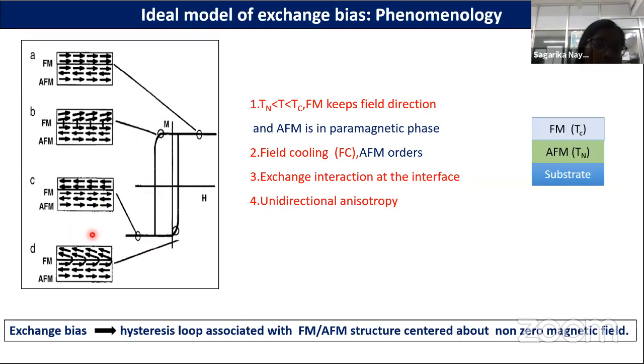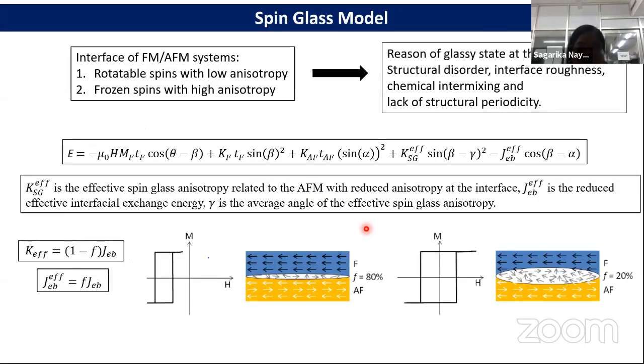But when the magnetic field is reversed to the positive saturation, the interface exchange coupling supports the alignment along the positive direction, so it requires a lower magnetic field to reverse. Therefore we get a shifted loop, and this is called exchange bias. But in this model, the magnitude of the exchange bias field is much higher than the value of the experimental results. Therefore next, I'm motivated by the spin glass model.